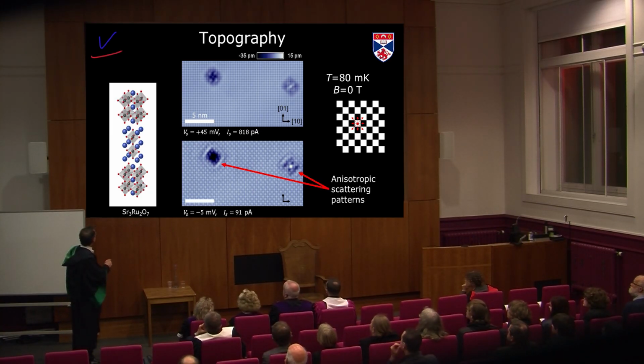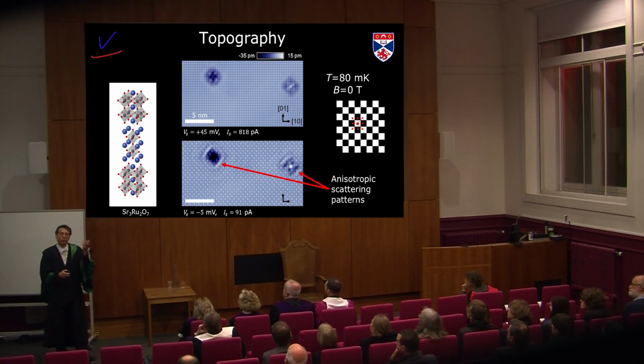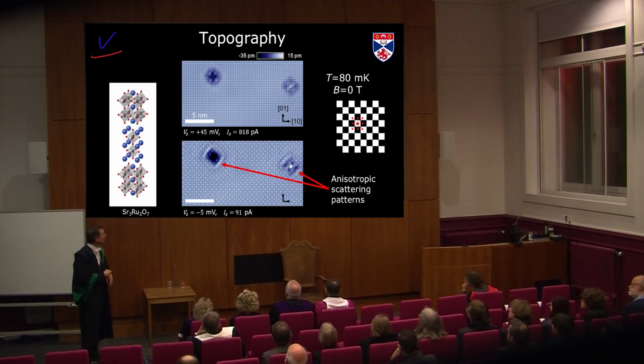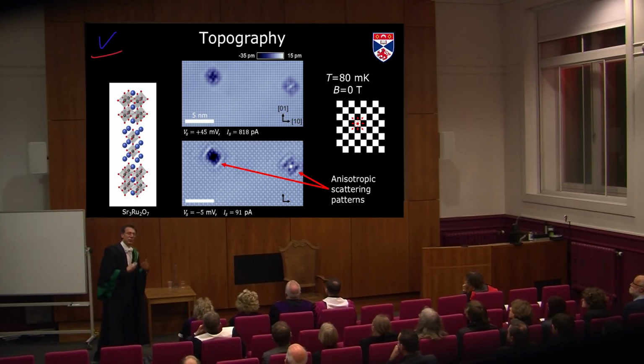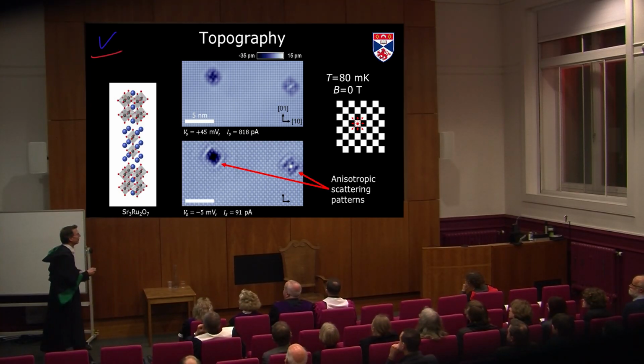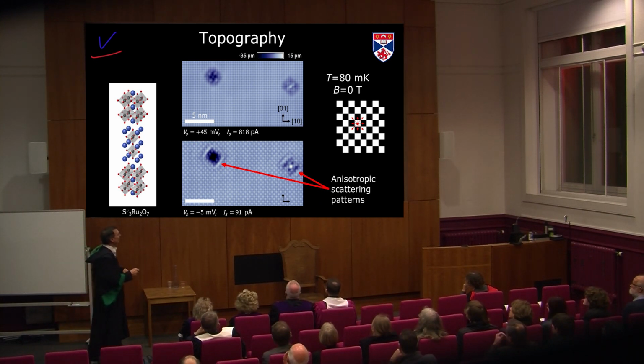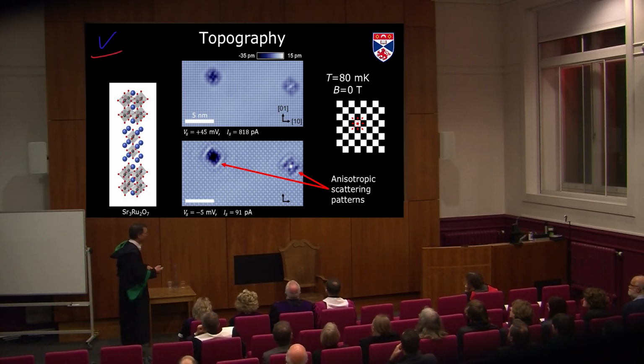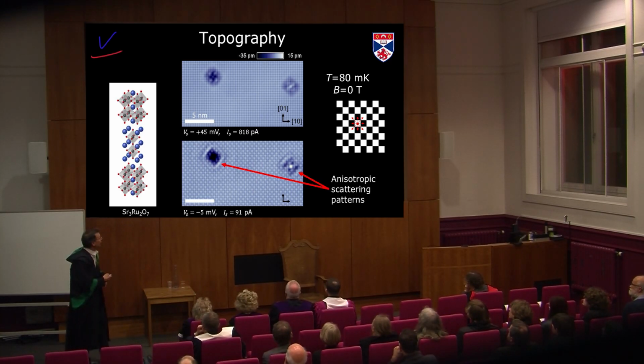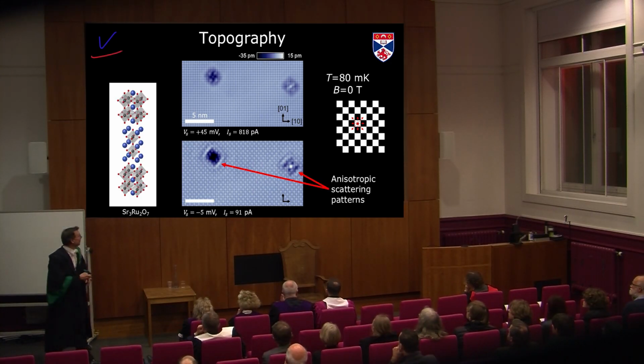Now, if I have a material like this, it has a fourfold symmetry. I can rotate it by 90 degrees and it looks the same. Then you would say that all the scattering patterns should have the same symmetry, right? So if I take a checkerboard and put myself, for example, on this white field here, if I go to the left, right, or top or bottom, that should all be equivalent. It should be the same. Likewise, if I go in diagonal directions, it should all be the same. It should be fourfold symmetric.